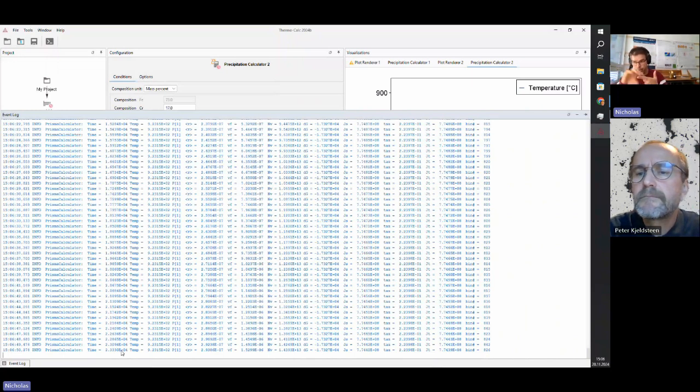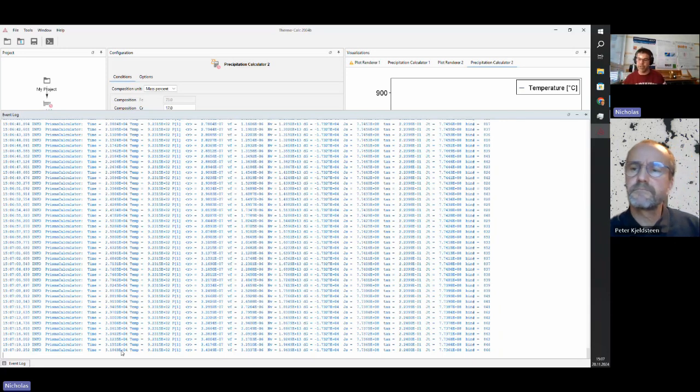Nucleation sites, but also interfacial energy is something. I'm now just using the calculated value, but that is absolutely unclear if that's a realistic value, right? And especially for these where you've got FCC nucleating and growing in a BCC matrix, one could assume that to start with you have some sort of coherent precipitates, right? Because maybe they're not so different, right? So they might start coherently when they're very small, and then move from coherent to incoherent as the precipitates grow, which would mean that you've got a far lower interfacial energy.